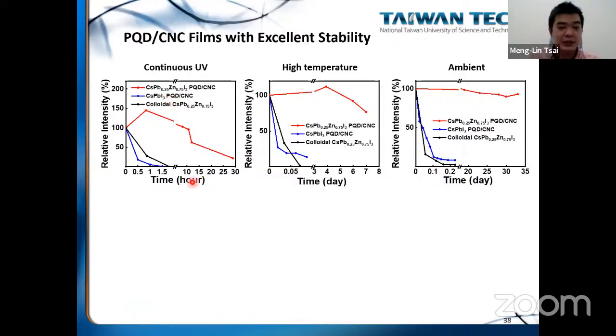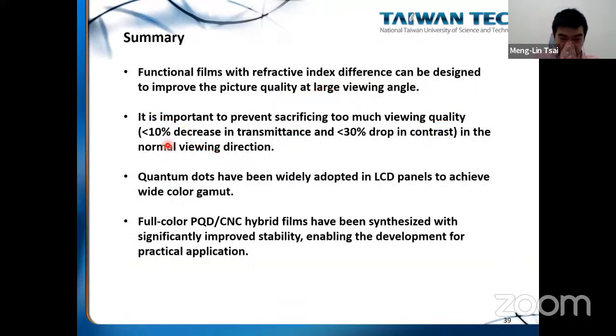Okay, so you can see that under continuous UV, high temperature and ambient condition, this doped perovskite quantum dot with CNC all shows better stability under these three conditions than the hybrid films without doping and the colloidal quantum dot. Okay, so this tells us that the cellulose nanocrystal is very effective in stabilizing the perovskite quantum dot. Okay, so this is a short summary.